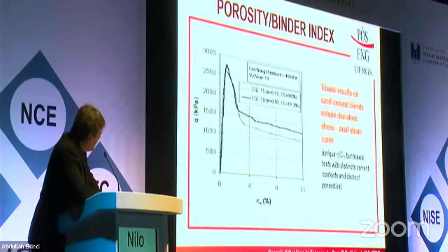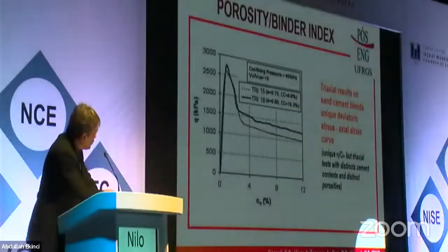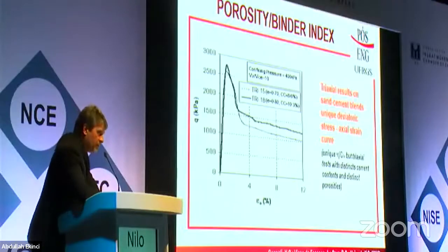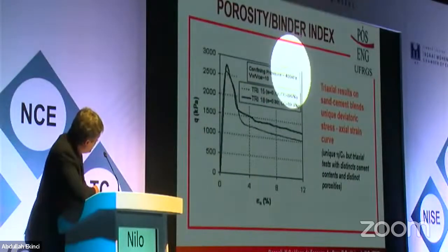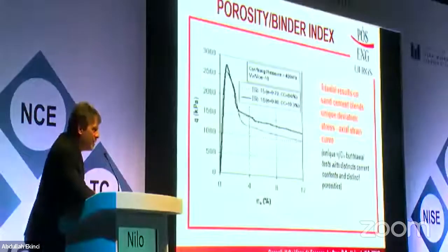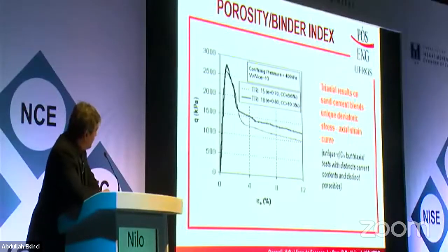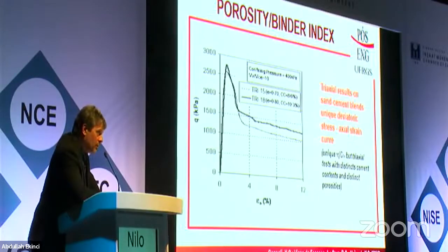Here is something also interesting that was published in 2009 already, showing that if we have, for example, these triaxial tests that were molded with different void ratio, different amount of cement, but the same eta CID, the same index, then under a specific confining pressure they have the same behavior from beginning to end. I mean, you can see the whole curve is the same, even though, as I told you, the void ratio and the amount of cement of both specimens are different. However, they have the same index.